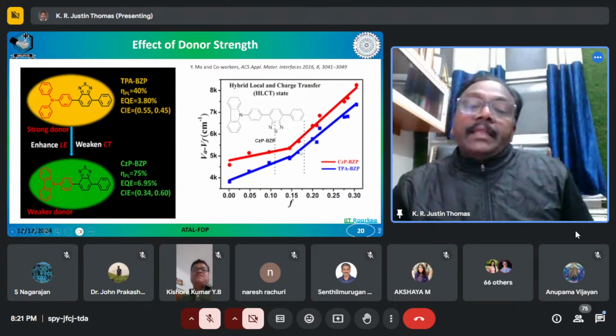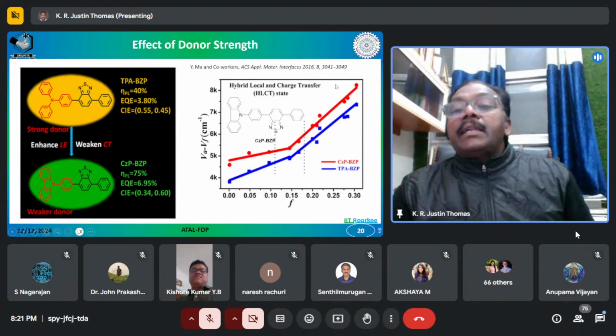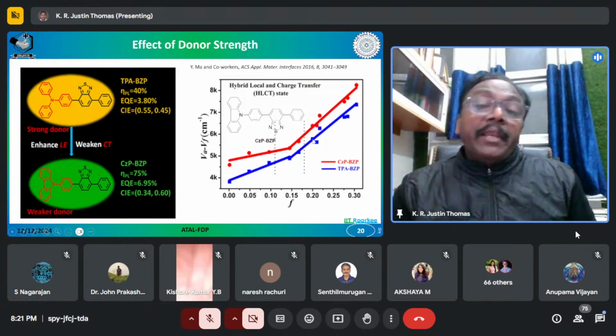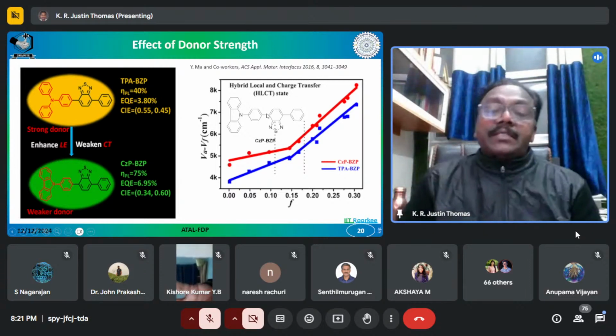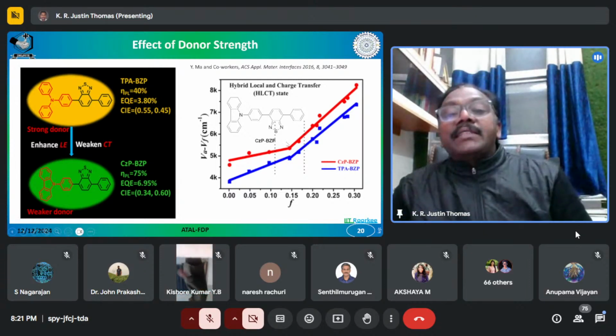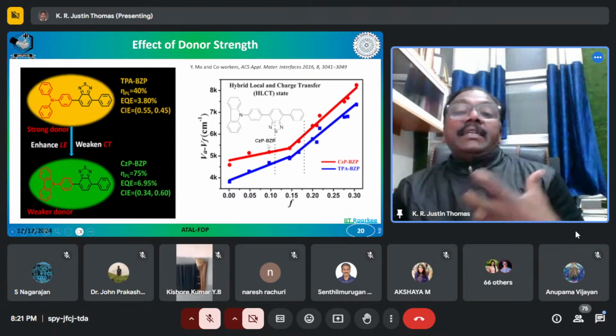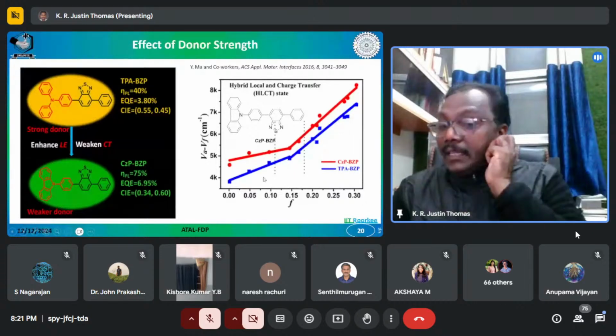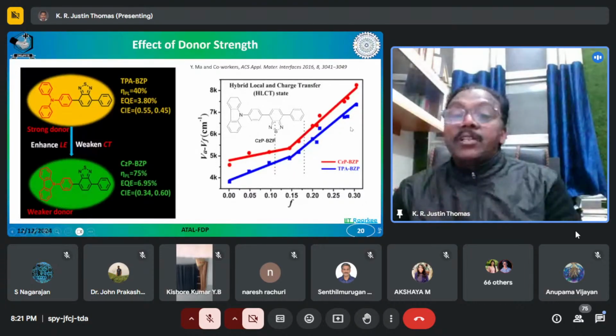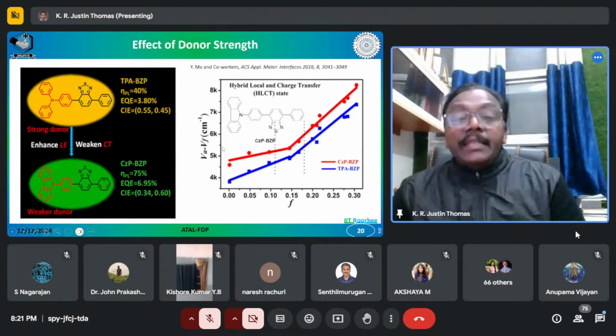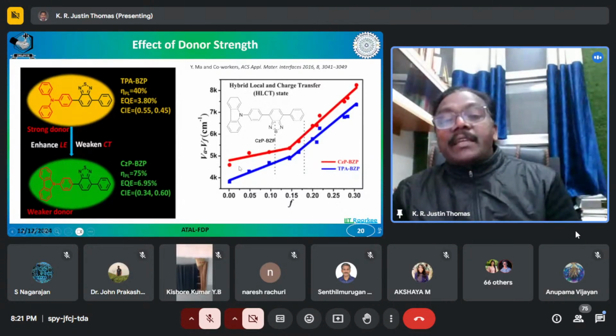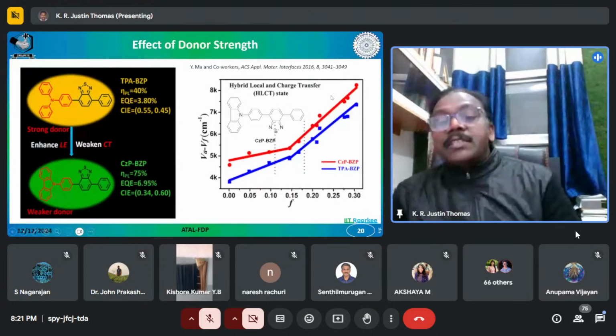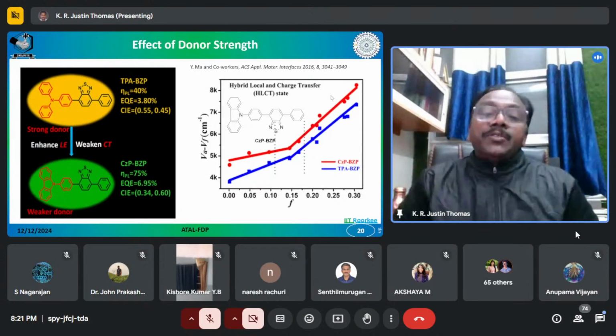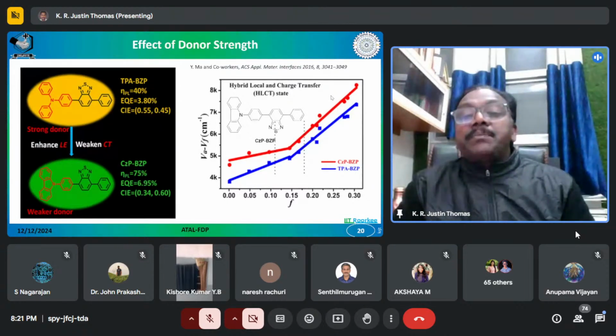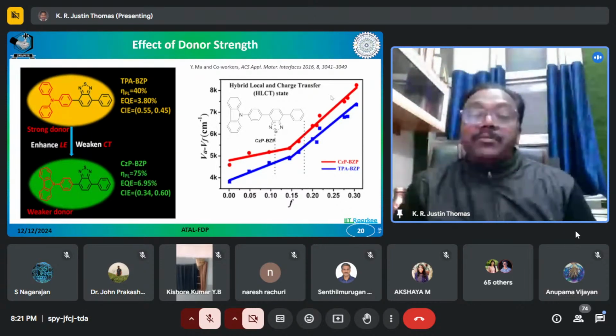Small slope in the non-polar solvent region and large slope in the polar solvent region. So that means that the molecule is having dual characteristics. They behave as a locally excited, non-polar molecule in the non-polar solvent and as a polar molecule in the polar solvent. That is mainly because in the non-polar solvent, it goes to the local excited state, and in the polar solvent, it goes to the charge transfer state. So that is a huge difference. So the observation of two linear relationships in the Lippert-Mataga plot is suggestive of an HLCT state in these molecules.